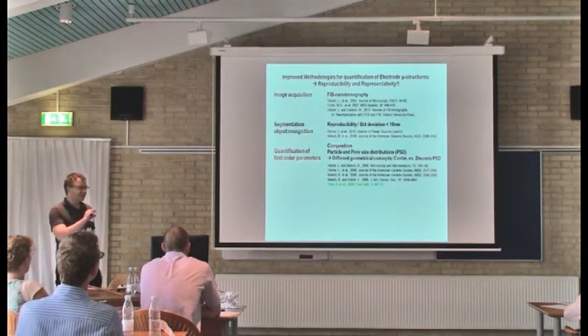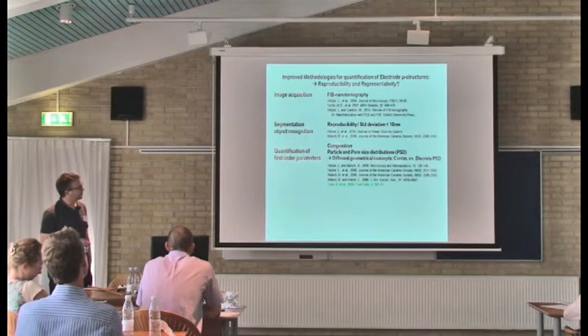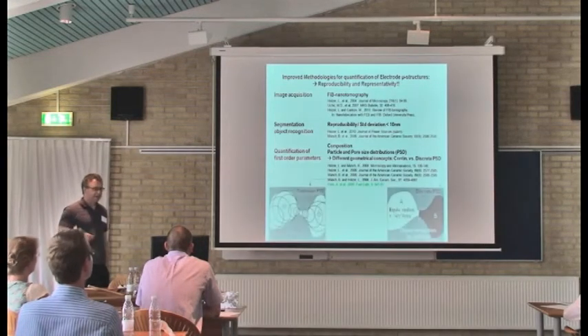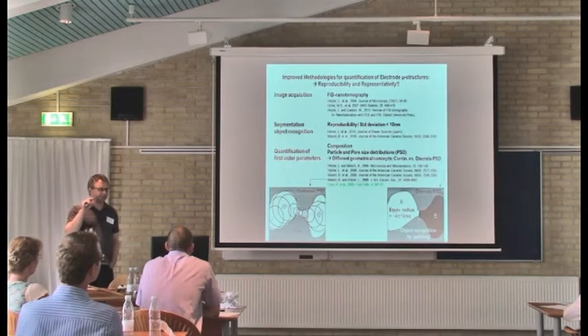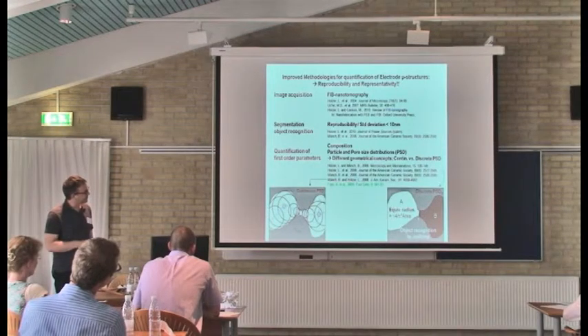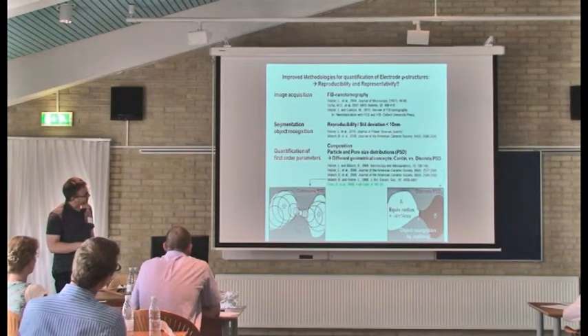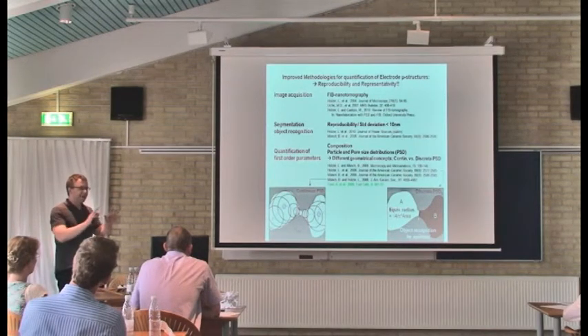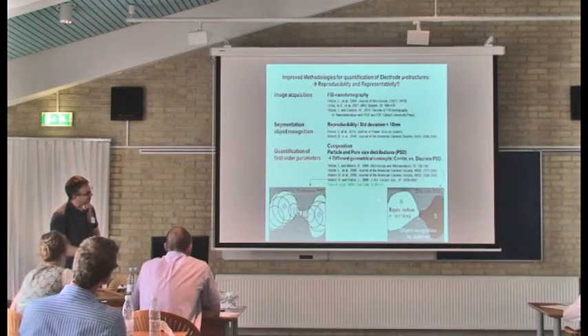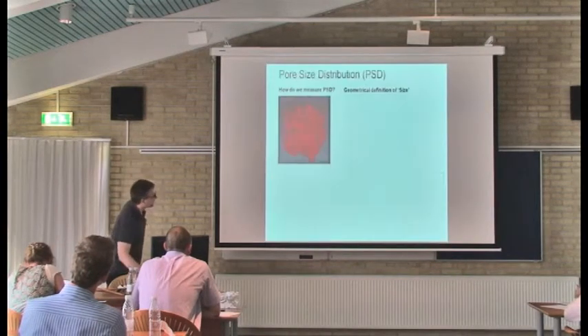Once we have identified our phases, we can start doing quantification. First-order parameters like composition are not a problem, but particle and pore sizes are quite challenging. It's important to realize that what we are measuring is very much depending on the geometrical concepts. We have done some work on these different ways and concepts of what the particle size is. We distinguish continuous particle sizes, where we consider the size distributions in a continuous network, or discrete particle sizes, where we try to identify discrete objects.